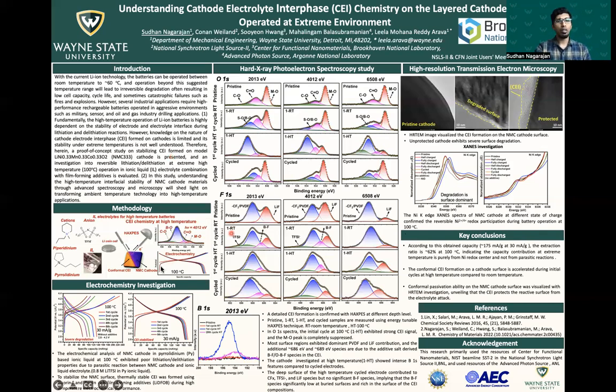As you can see in the electrochemical investigation, we investigated the NMC cathode in ionic liquid electrolyte. We conducted the electrochemical charge discharge studies, and as you can see, the NMC cathode was severely degraded at high temperature operation at 100 degrees Celsius. Even though the ionic liquid is thermally stable, the electrochemical interaction at high temperature is not favorable.